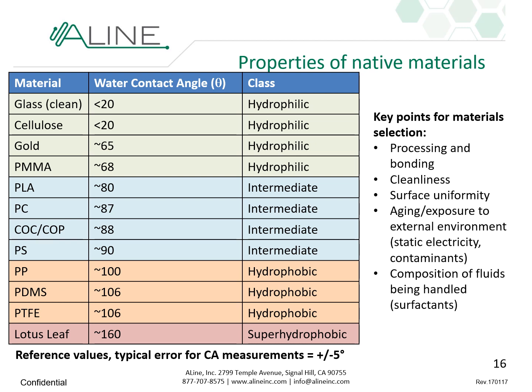And then there's also to keep in mind that this is for DI water. So if you're using different fluids like water with surfactants, ionic fluids, or other components that are not DI water, this number might actually change. So you might not need to really focus only on these numbers, but take them with a grain of salt and think about the overall application.